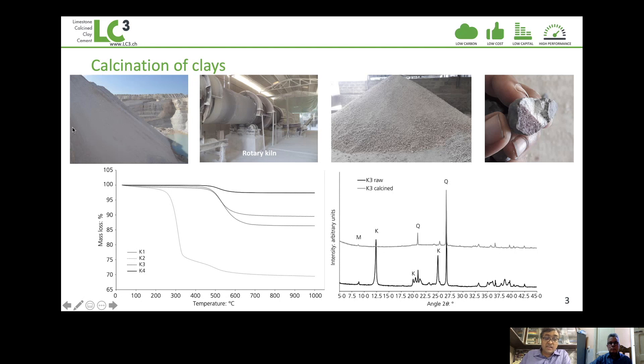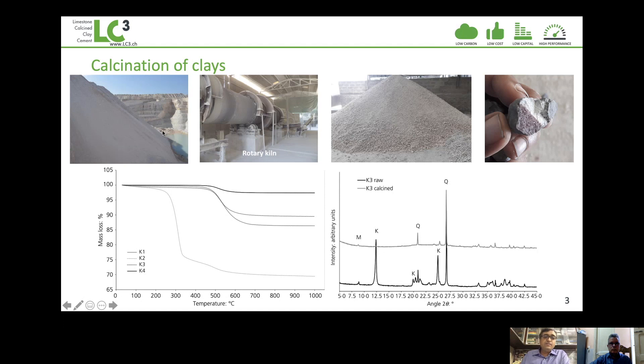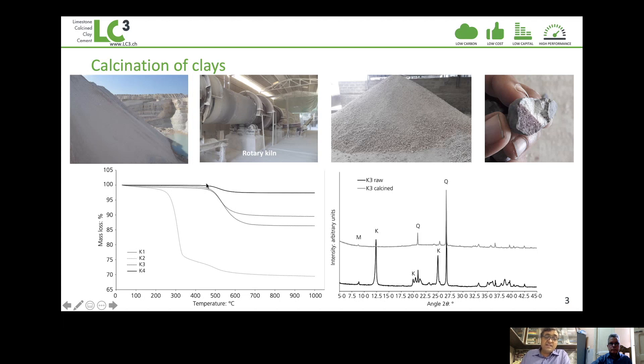In calcination, you take clays. A lot of people are worried because they think good quality clays aren't available everywhere. When you think of clay, you think of China clay, which is used for ceramics and papers and high-end applications. But here we're talking about waste clay from mines — the kind found almost everywhere in the world. It's a clay with a lower kaolinite content than China clay. Kaolinite decomposes at 450 to 650 degrees centigrade, losing water and changing its crystal structure.